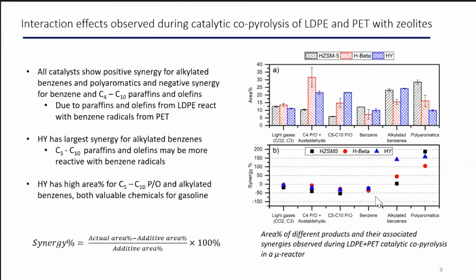So what we believe is happening is that the benzene from the PET pyrolysis is reacting with the C4 to C10 paraffins and olefins from the LDPE pyrolysis to form the higher amounts of these alkylated benzenes and polyaromatics. And if we look at our alkylated benzenes, we can see that the level of the synergy is dependent on the catalyst. We see that the HY has a very high synergy percent for alkylated benzenes, which is very beneficial because these alkylated benzenes, such as toluene, can serve as octane boosters for fuels.